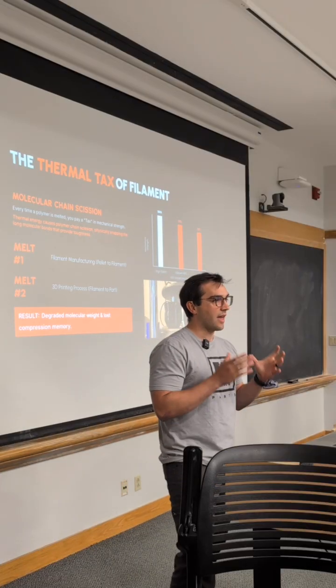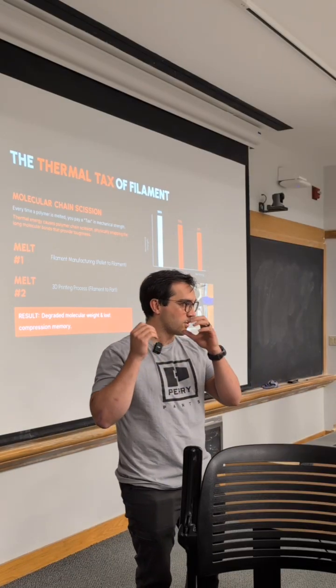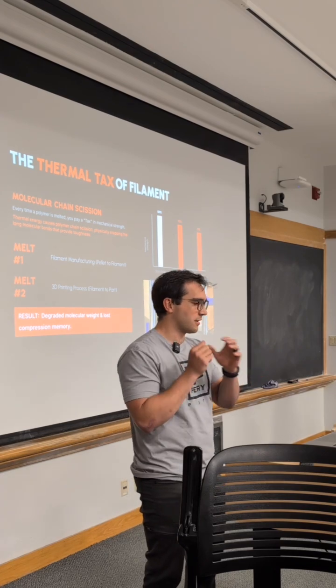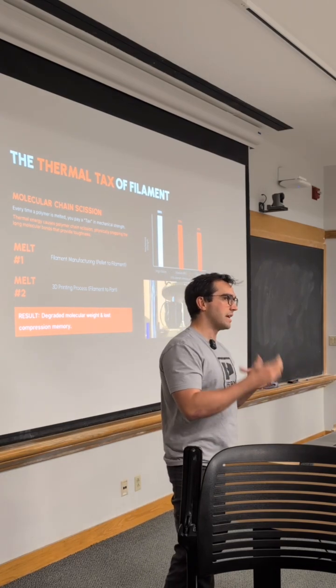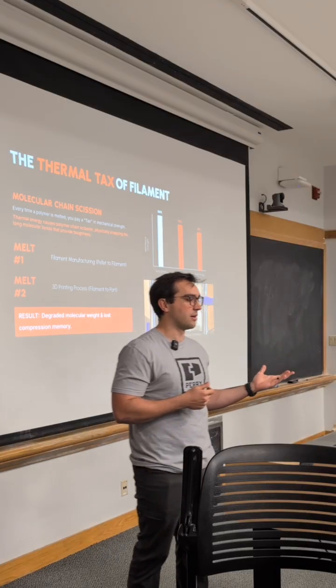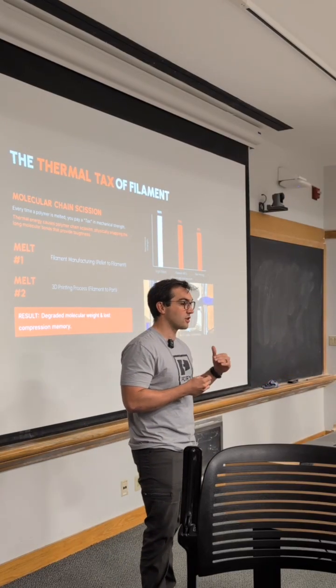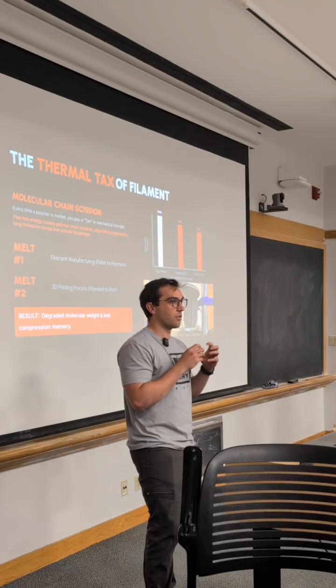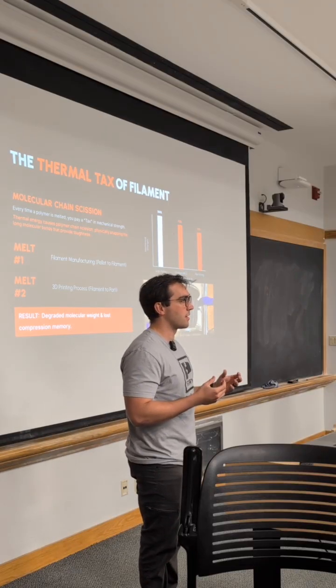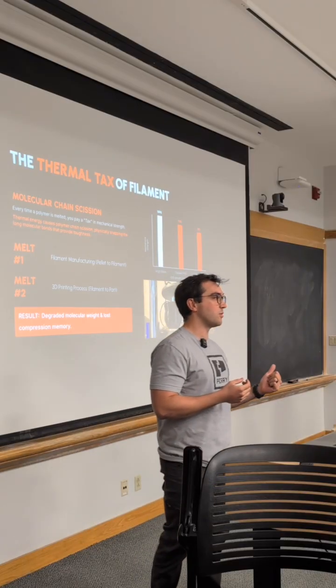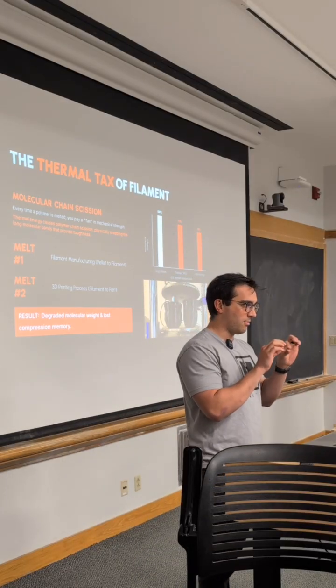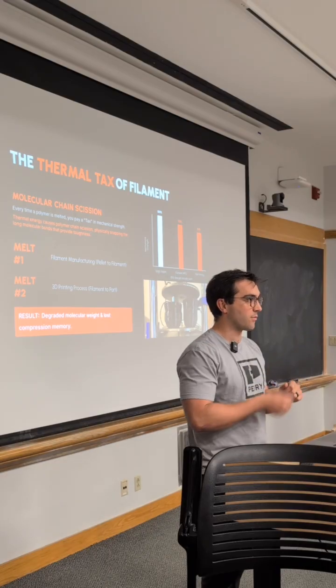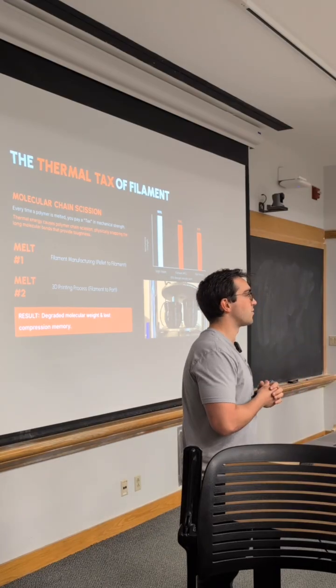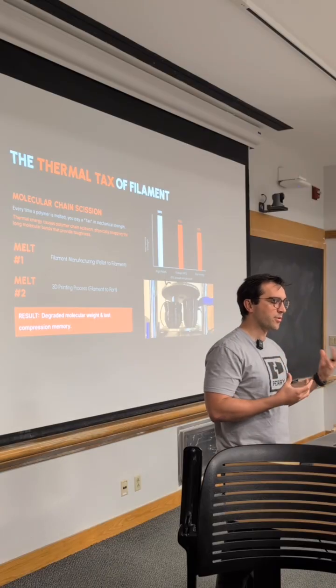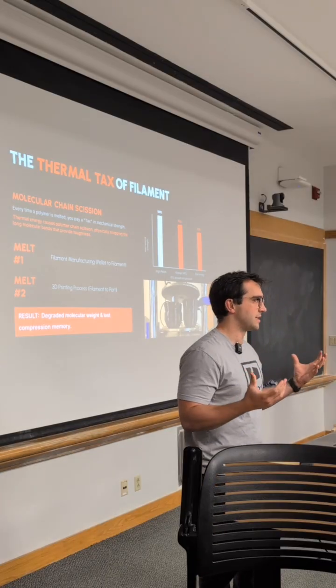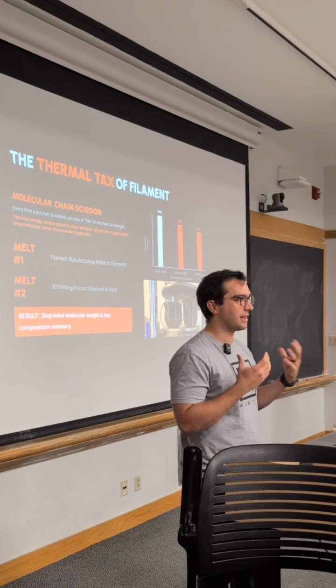The limitation there is every time you melt a polymer, not only does the screw in the filament extrusion line break up that polymer chain, but you also go through polymer scission, or molecular chain scission. So the polymer chains get broken down a little bit, the material loses some of its properties. Particularly with elastomers, you lose a good bit of elongation at break. So that's how much you can stretch that polymer before it finally gives way. And you do lose a good bit of ultimate tensile strength as well. So you can almost think about it as like embrittling your material, right? It gets just a little bit harder to work with and a little bit less durable and tough.